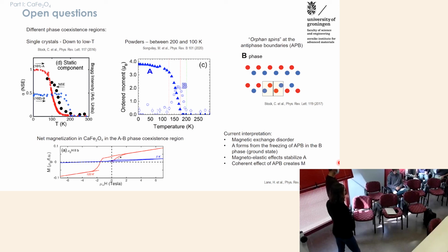And iron gives a huge magnetic signal in this measurement. So all magnetic measurements should be somehow affected by the presence of the big signal from iron. Where does this signal appear in your magnetization loops and in your Mossbauer?